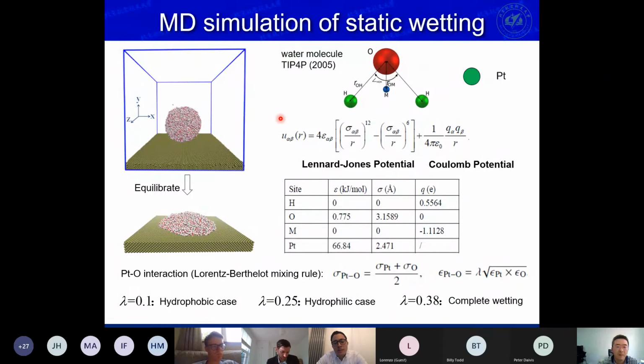Because we simulate water droplets, we use the TIP4P/2005 model to simulate water. In this model, for each water molecule, there are 4 sites, one oxygen site without any charge, 2 hydrogen sites with positive charge, and 1 M site with negative charge. And the interactions between water molecules are based on both Lennard-Jones potential and Coulombic forces, and the Lennard-Jones potential is applied between the oxygen sites, and the Coulombic forces are applied for all the sites that have charges.